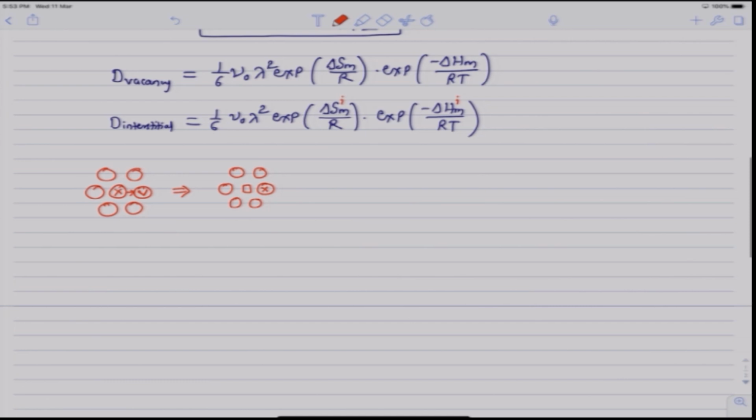because the next jump of the atom X is no more random, it depends upon the previous jump, and these are called correlated jumps. Now, the same vacancy can exchange with atom X multiple times, and such a sequence of jumps of an atom into the same vacancy again and again is called a correlation chain or a correlation sequence.